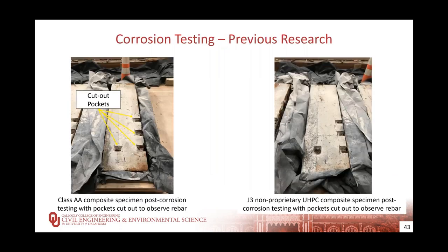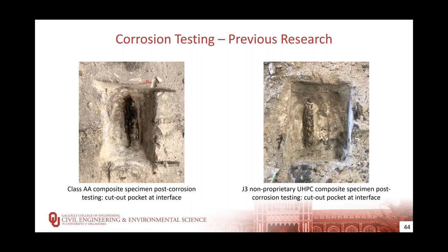From previous research conducted at OU, similar tests were carried out for repaired composite specimens. These are two composite specimens, one class AA mix and one J3 mix. Here you can see the pockets that were carved out to check on the corrosion state of the rebar. These are the same specimens with close-ups of the window cut at the interface of the two materials.